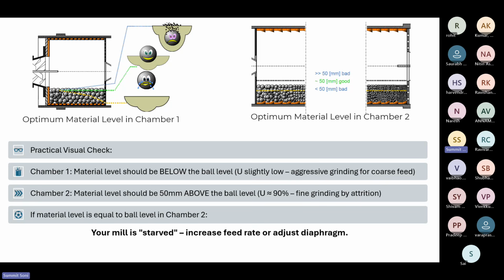Same thing in the second chamber. The minute you enter the second chamber, you see the level of the material on top of the ball, which should be somewhere around 40 to 50 mm. If it is around 50 mm, it's the perfect condition. Your mill is getting the right amount of feed. It is doing the right kind of grinding. The first chamber is doing the right kind of grinding. Your diaphragm is doing well. There is no jamming, no choking, nothing.